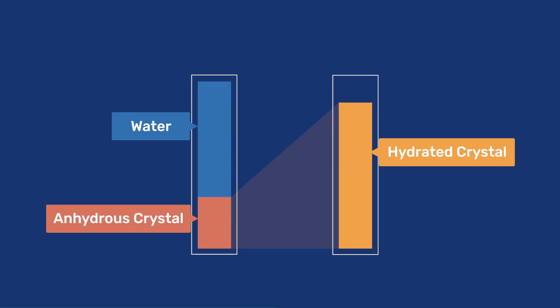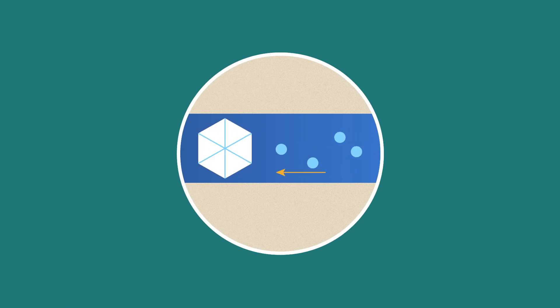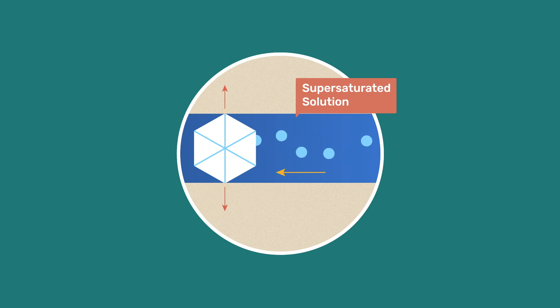In particular, in the formation of hydrates, the product is larger than the reacting solid, which easily leads to incorrectly concluding that this change in volume causes the damage. Rather, it is the growth of the crystal, driven by supersaturation of the solution, that allows the salt to exert stress on the pore walls with potentially destructive results.